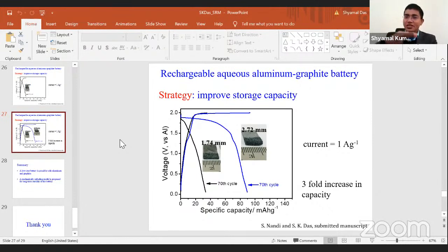So that is why, with time, not a continuous increase, but after a few cycles, 10 cycles or maybe 15 cycles, you see an increase in capacity and later on it stabilizes. So that is one reason. The reason, to be very precise, is that with time, the expansion of the graphene layer increases, and that helps in accommodation of more aluminum ions inside the structure. I hope I could clear it.